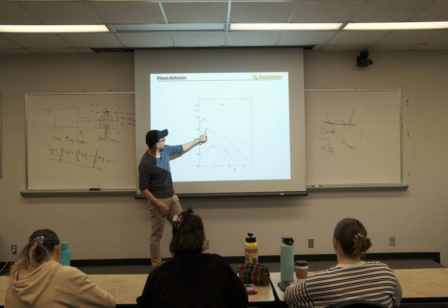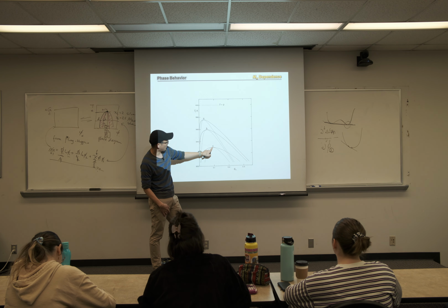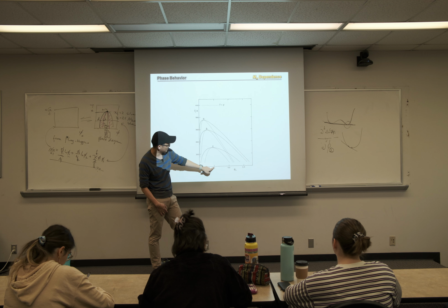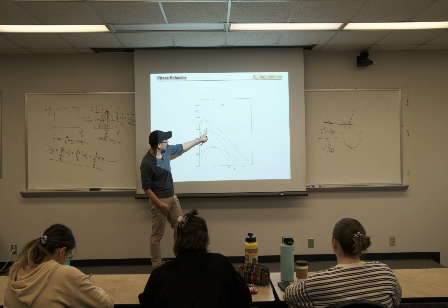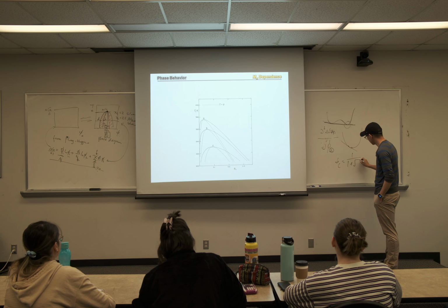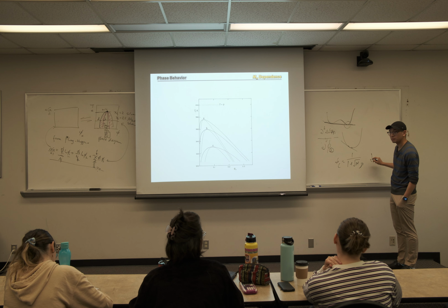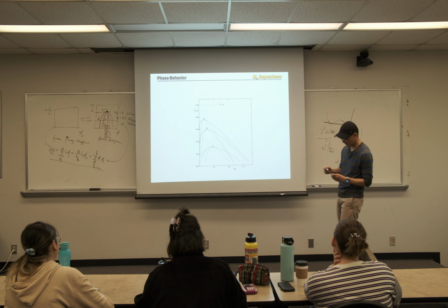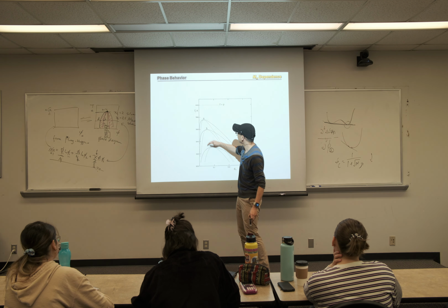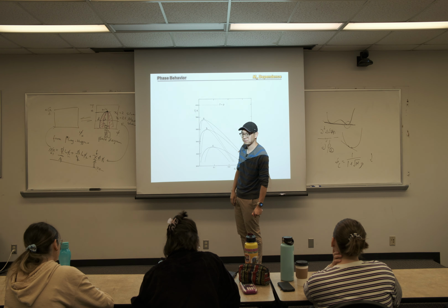So when we keep increasing the molecular weight, your phase diagram will go from a critical concentration of 0.1 to even lower. I explained how this all depends on phi c equals 1 divided by 1 plus root n. So when n goes up, your phi c will drop, okay? That explains why high molecular weight shifts to this region.